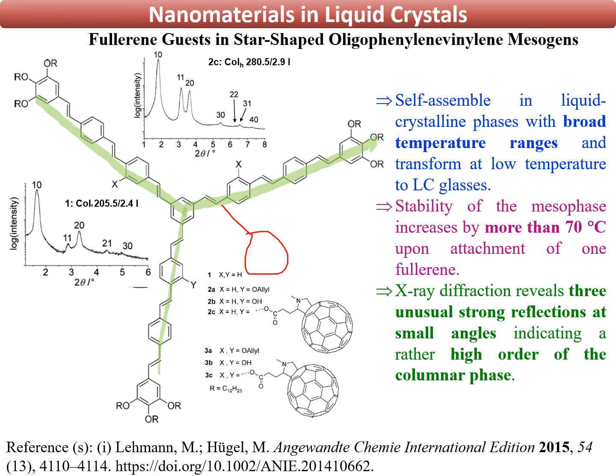As can be seen from the small angle X-ray diffraction, the presence of three additional strong peaks indicates a high level of order in the columnar mesophase.